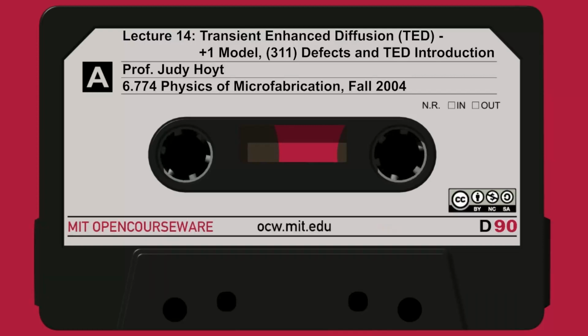So you'll see people, prior to a shallow boron implant, implant silicon at liquid nitrogen temperature or germanium at room temperature to create an amorphous layer. Into that amorphous layer, implant the boron, and then do a relatively low temperature activation to try to activate the boron and get a little bit better annealing behavior.